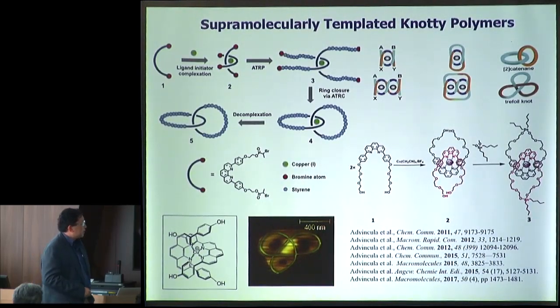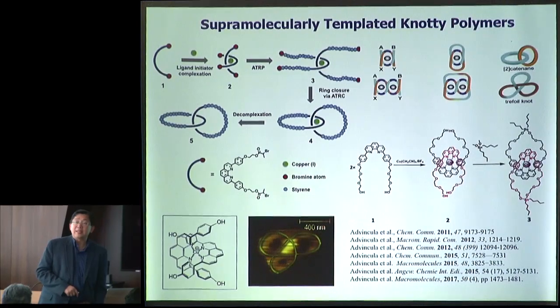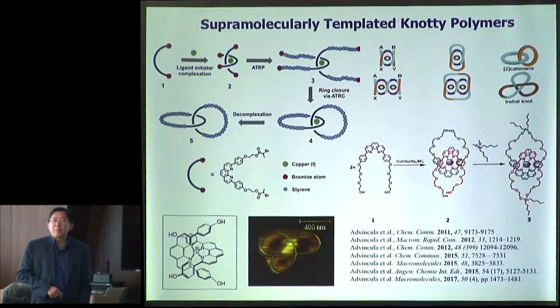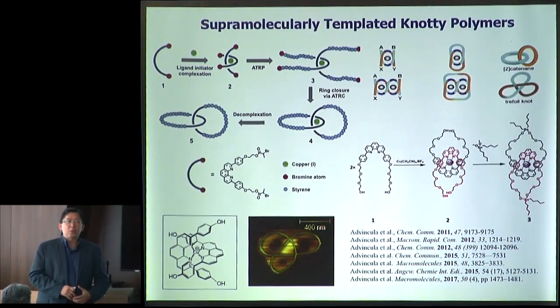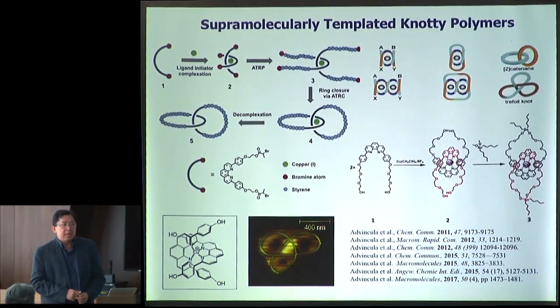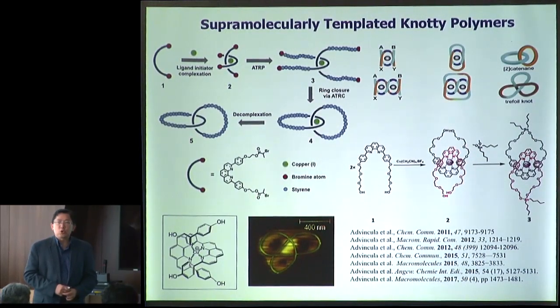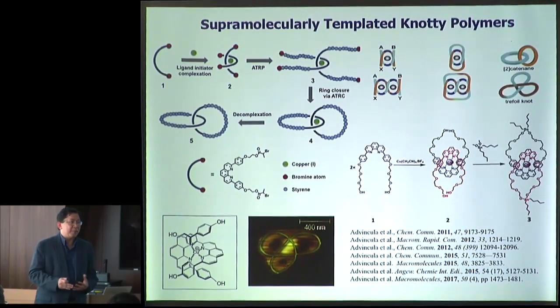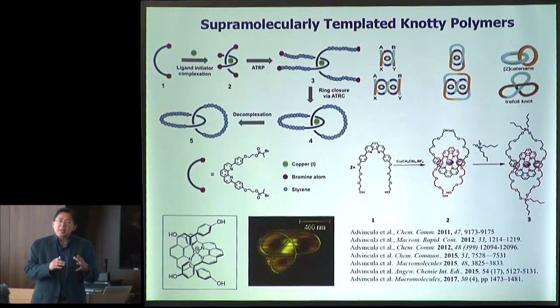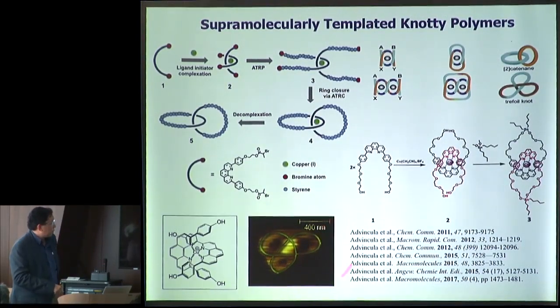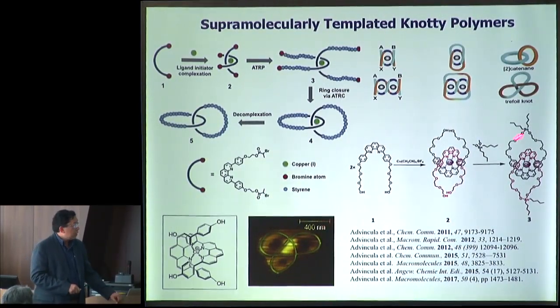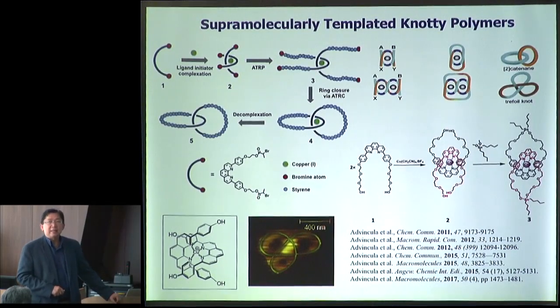In another aspect, and this is more recent work, we like to use supramolecular templating, where we take various types of supramolecular structures and then grow the ring towards what we call catenated and knotted polymer systems. As some of you may recall from the work in supramolecular chemistry, that means the ability to control the orientation or donor-acceptor or even hydrogen bonding type of interactions to lock in a particular topology. And then in our case we want to grow them, such that we have reported, for example, the first polycaprolactone trefoil knot through a bidentate ligand design. So this just tells you that everything starts from the molecular to macromolecular level.